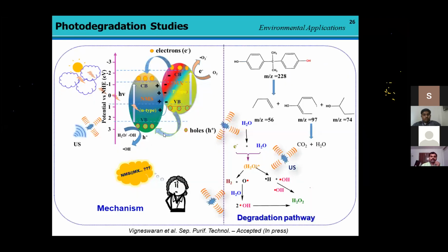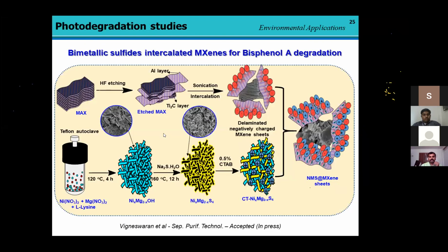Then, when I was in South Korea, one of my juniors, Vigneshwaran, came to South Korea for his internship program. Then we started some bimetal sulfides. There are also 2D materials intercalated on the MXene material for bisphenol degradation, where we have successfully got results for the intercalation. We synthesized nickel magnesium layered double hydroxide, which was further treated with a sulfur moiety to get the sulfide form, which is more beneficial.